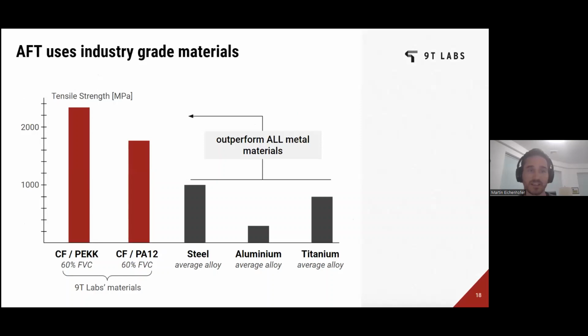You see the tensile strength is what you would know from the most structural fiber composite materials, 60% fiber volume content. So it's a real composite. It's not just something like, oh, we added some fiber and you have, I don't know, 400 or 500 megapascal tensile strength. And it can outperform all metal materials, yes, but all in this group in particular, I guess we all understand that it's only good if we leverage the fiber and the strength of the material in the right way, right? Optimize the part.